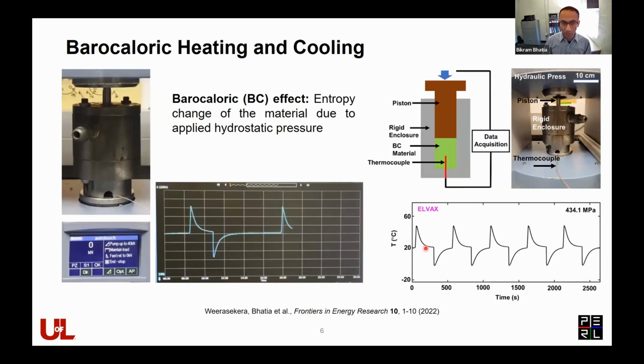One representative result is shown here for a material known as Elvax, which is a thermoplastic elastomer. You can see operating around room temperature, the lowest temperature you can get to is around 0 degrees Celsius. So it's a pretty substantial temperature change of about 27 degrees Celsius or so.